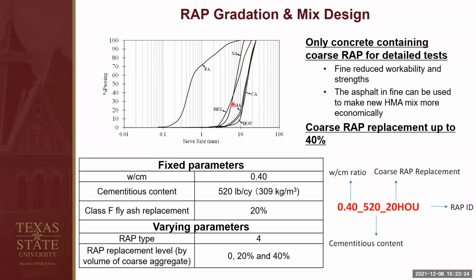For San Antonio and Bryan, the gradation was finer than the coarse aggregate and Amarillo and Houston sources. So they were mostly intermediate particles in the gradation. And we also have our sand plotted here. As you can see, sand is much finer than those coarse aggregates. For our mix design, we only used coarse RAP to replace coarse aggregate by up to 40%.